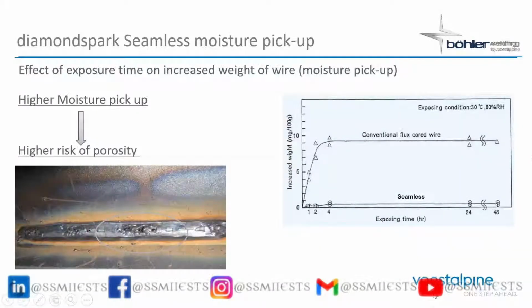So basically, with higher moisture pickup, the chance of porosity and therefore repair is very high. And this is what we wanted to avoid with this new manufacturing technology called seamless flux cored wires. And you can see the seamless wires, even over long exposures of 24, 48 hours, the hydrogen levels are less than, let's say, 2 or 3 milliliters per 100 grams.